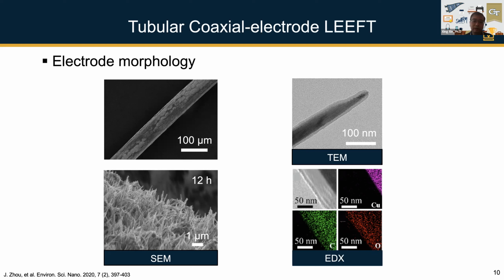It will affect the electric field distribution, and eventually, if it's too thick, it's not going to work. So that's why we control the coating layer by the coating time and also the dopamine concentration in the solution. We can control the thickness fairly well in the nanometer scale. Eventually, the best performance we got is about 50 nanometers. As you can see here, this thin coating layer is about 50 nanometers thick. So it doesn't affect the morphology of the nanowire structure that much, but at the same time, it provides enough protection.